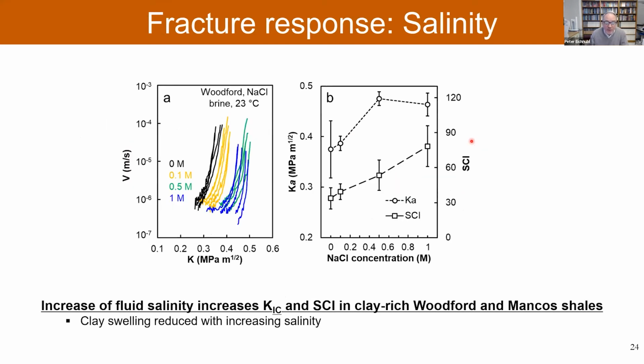Now, if we have water and change the salinity, as you may expect, for those of you who are familiar with how brines interact with shales, as we go up in the concentration of NaCl, both the fracture toughness, which is the short dashed line here, and the subcritical index go up with increasing salinity. So an increase in salinity actually makes the shale stronger, in the clay-rich shales, not in the carbonate, where there's no effect.